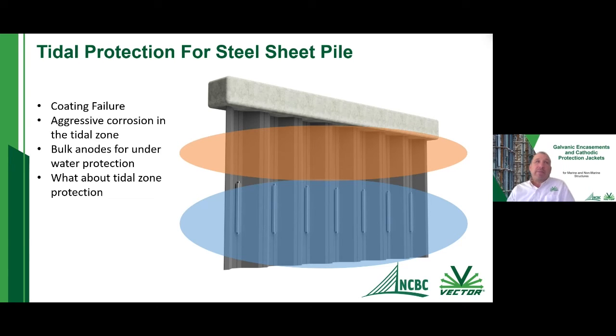Now, what ends up happening is you have this tidal zone. So this is that tidal zone that's above the bulk anodes, and it's a very, very difficult area to protect. So you get a lot of coating failures in this area, as I showed you in the previous picture. So what can you do to actually rectify this situation once your coating starts to fail and you have corrosion that's occurring?